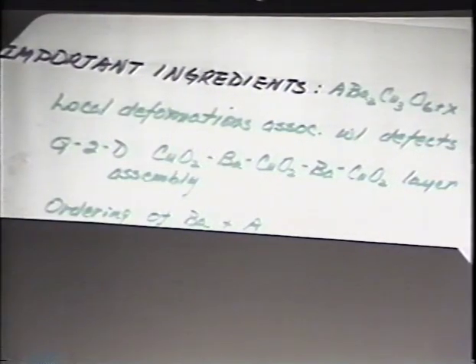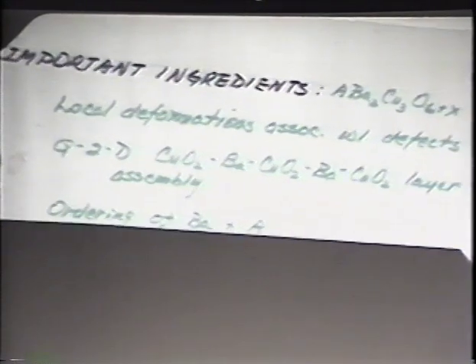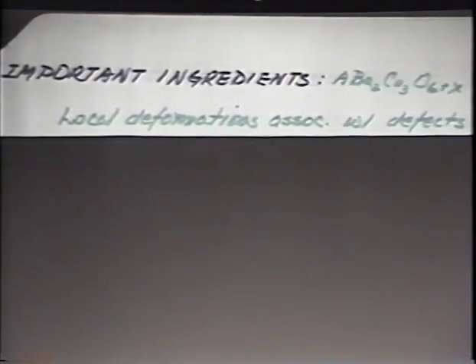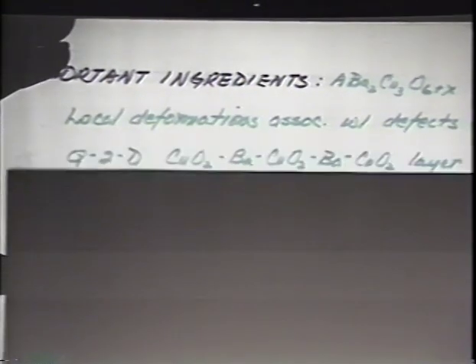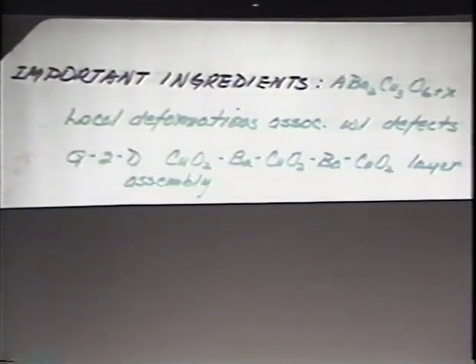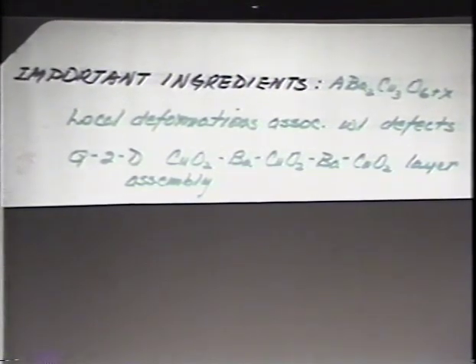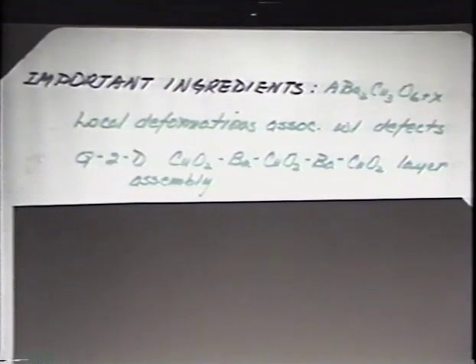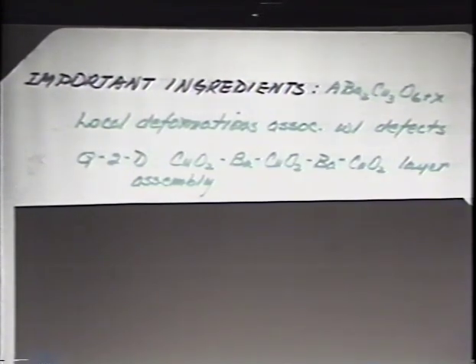Okay. So now, with all those results, what are the major ingredients in the superconductivity of this class of material? It appears to us right now all these structures have some defects, and therefore there must be local deformations associated with defects in here, so it must be important. And the second thing is all that assembly of layers over there, it retains some kind of quasi-2-dimensional characteristic, because when you change the A elements, you don't change the superconductivity. So it indicates that perhaps those 3 layers do not really couple strongly. It retains some 2-dimensional characteristics.